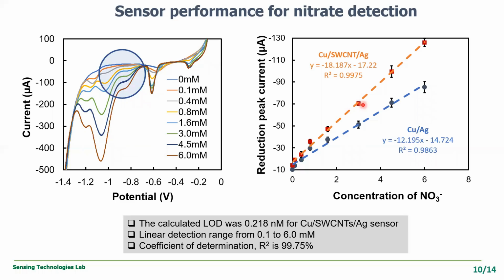To get the calibration curve, the reduction peak current of nitrate was plotted against different concentrations of nitrate for both sensors, and the LOD was calculated and found to be 0.218 nanomolar for this copper CNT silver sensor, which was lower than the copper silver sensor. The linear detection range was from 0.1 to 6 millimole for both sensors, and the coefficient of determination was higher, 99.75%, compared to the normal copper silver sensor.